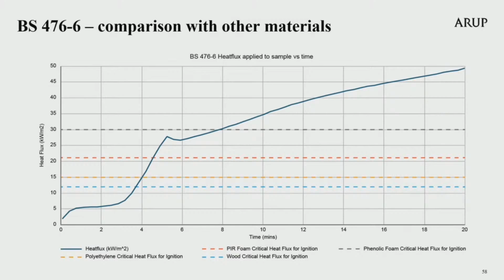I note that the melting point of polyethylene is approximately 130 degrees Celsius, whereas the melting point of aluminium is over 660 degrees Celsius. Based on the test reports submitted to the inquiry, when ACM panels are tested in this apparatus, the aluminium can sometimes act as a protection to the polyethylene, protecting it from direct flame exposure, and therefore the polyethylene sometimes melts and flows away rather than ignites within the panel during the test. If it does not ignite, the temperatures measured in the chimney are lower.